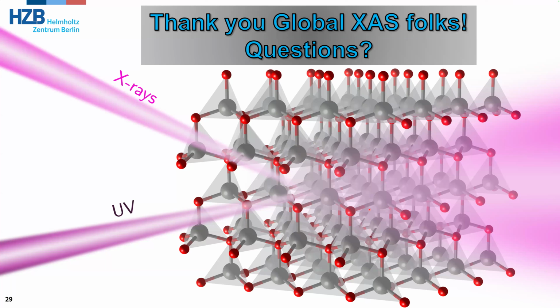How does that work at the L edge? Yes, so at the L edge, the sample is in a gas cell, as I described earlier. So there are actually thermal contacts on the substrate, so you can actually heat it up this way. It's on some copper conducting surface, and you can heat up your sample this way, and you measure in transmission. Yeah. Okay.